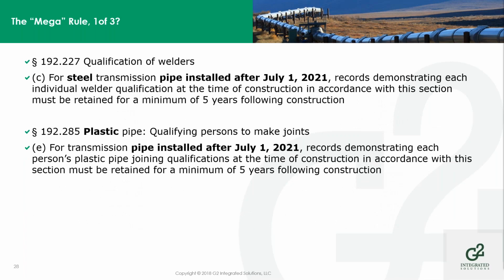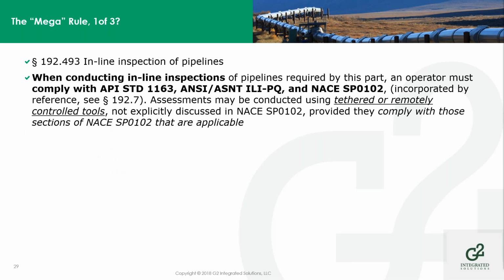Again, qualification of welders. This section was added for steel transmission lines. You have to maintain those records for pipe installed after July 1st for 5 years. For steel transmission, and for plastic pipe, same thing. After July 1st, 2021, they have to be maintained for a minimum of 5 years following construction. Inline inspection has to be done in accordance with API 1163 or ANSI ILI PQ and NACE SP0102. You may also use tethered or remotely controlled tools, not addressed specifically in 0102, but you must comply with the sections of the NACE standard that are applicable, even though it's a tethered or remotely controlled tool.